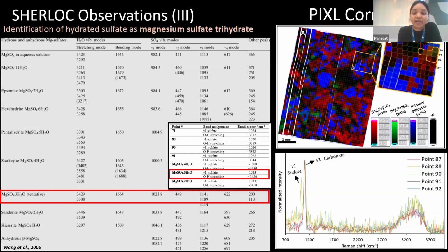We did not really compare the hydration band because a wave number shift is something we expected, because sulfate hydration is co-occurring with carbonate hydration. And talking about that, in the figure on the right, we found that when sulfate is present, the intensities of hydration bands are higher compared to when sulfate is absent. That clearly indicates that sulfate is hydrated. Also, the intensity of the OH band is not correlated with sulfate V1 intensity, indicating that these two components contribute separately to the hydration of carbonates and sulfates. Next slide, please.